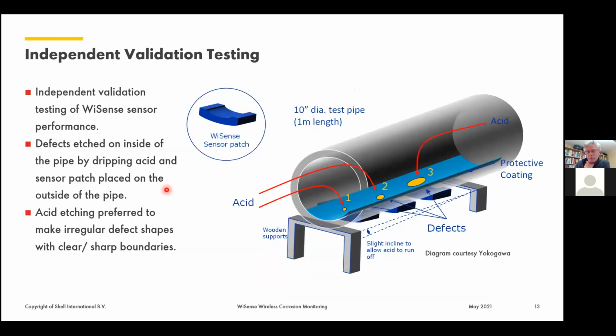But then when you want to do the real testing, you want to have the patch left in place, which means you have to introduce the defect on the other side. And if it is a pipe, you need to create access in the pipe with etching agents, letting the etching fluids run off after you drip them onto the defect area. And this creates a fairly tedious process, which is something that comes with permanent sensing techniques. And we see that with other sensing techniques as well. You run one test and then the defects have grown to a certain depth, and then you put the pipe aside and start with a new one to generate a second test.